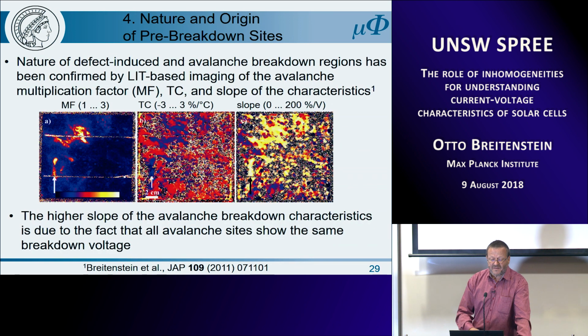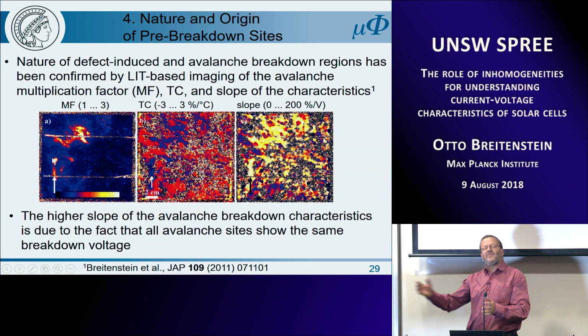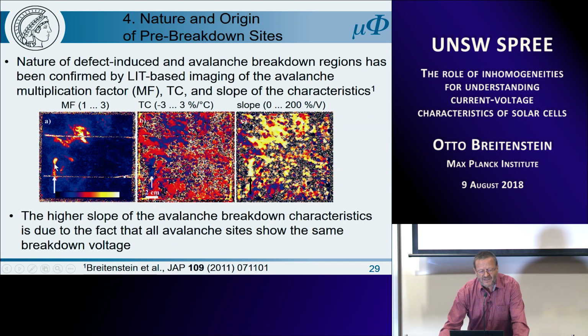defect-induced breakdowns, in particular the proof between avalanche and non-avalanche, can be done by special lock-in thermography methods which allow to image the multiplication factor. And here we see where we have only this high voltage breakdown, we have a multiplication factor much larger than 1. 1 would be no multiplication. And also the temperature coefficients are different and also the slopes are different. So this all can be measured.